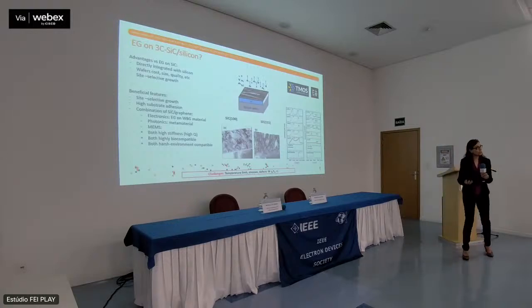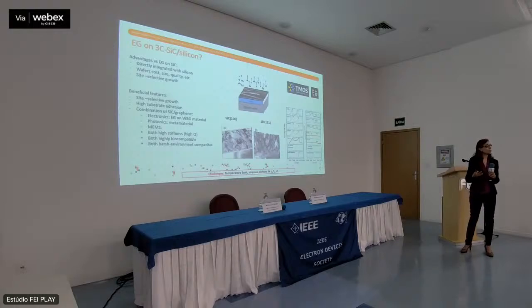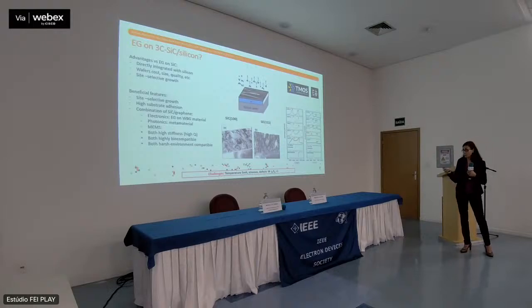As you can see here, for those of you that are familiar with Raman spectroscopy of graphene, which is the quickest way to have an idea of what type of graphene we have, whether it is quality or not, you focus on this part of the spectrum, so D and G are typical fingerprints of graphene. In principle, if the layer was completely defect-free, you wouldn't have this D band. And the fact that you have a D band, and that this D band is really high, even higher than the G band, means that your layer is highly defective, potentially not even continuous. And this is usually what happens, unfortunately, if we try to translate this process to silicon carbide on silicon.